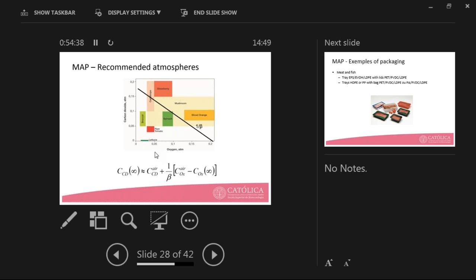In this picture we can see some recommended atmospheres for different products, vegetables and fruits, where we have a window, a range of oxygen and a range of CO2 concentrations for each product. For example, in this case, for strawberry, we allow 5% to 10% oxygen and 15% to 20% CO2. We can see here a black line, represented by the equation that you can see at the bottom of the slide, with a slope that is the inverse of beta, the ratio of CO2 permeability to oxygen permeability.